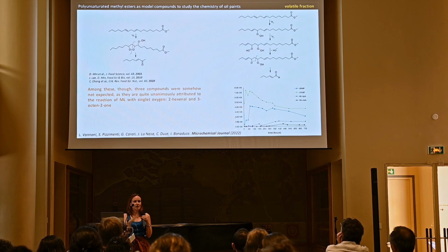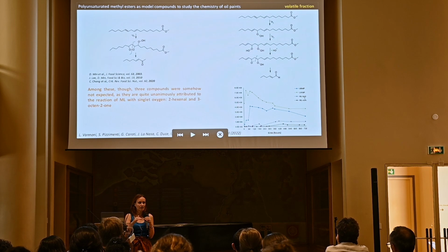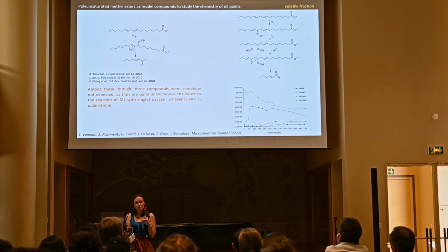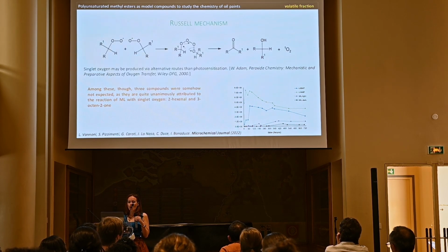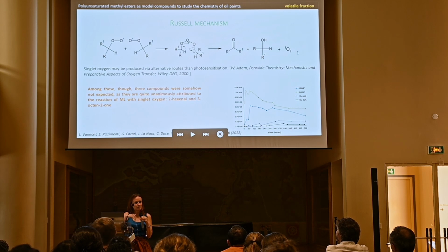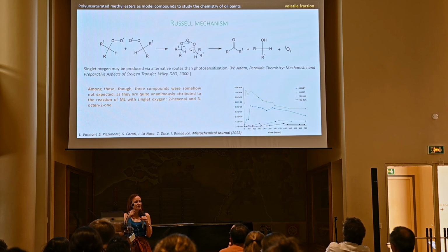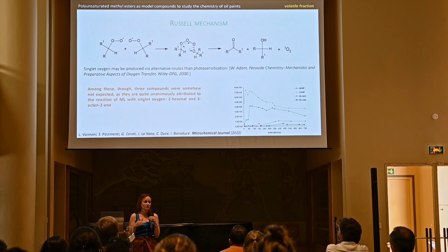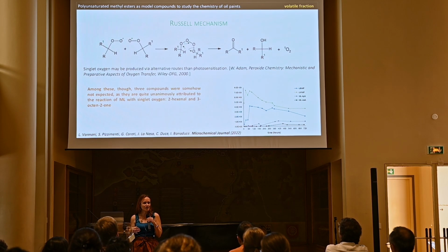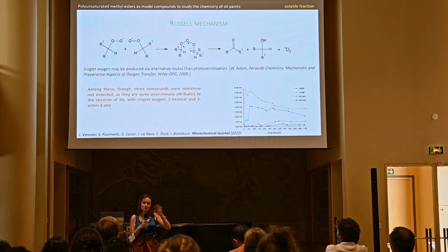Anyway, we see the same compounds for lead white, for ultramarine blue, but also for methyl linoleate kept in the light and in the darkness. So this has got nothing to do with photosensitization, and is probably just produced on site. For example, the recombination of peroxide species may produce singlet oxygen on site in the paint layer. Now, this is interesting because singlet oxygen is very, very reactive, and so will push oxidation even further and oxidize the environment around it. But still, it's not a difference between lead white and ultramarine blue because it was present in both cases.